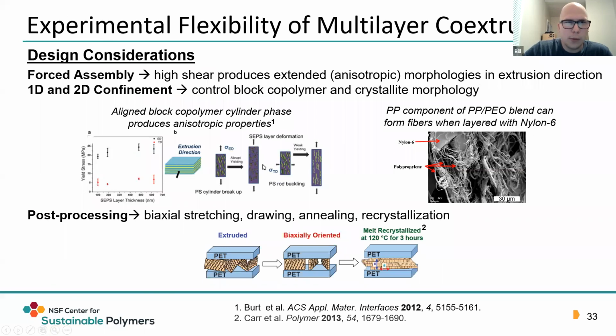Some special design considerations here are the combination of high shear and layer confinement that allows you to get this forced assembly. For example, in a block copolymer system, alignment of a cylinder phase with the extrusion direction, and in a blended phase of polypropylene and polyethylene oxide, you can actually get the polypropylene to form a continuous fiber forming phase. Further processing can control the morphology with confinement effects beyond that, giving you a 2D confinement instead of the 1D confinement typically seen from spin coating.